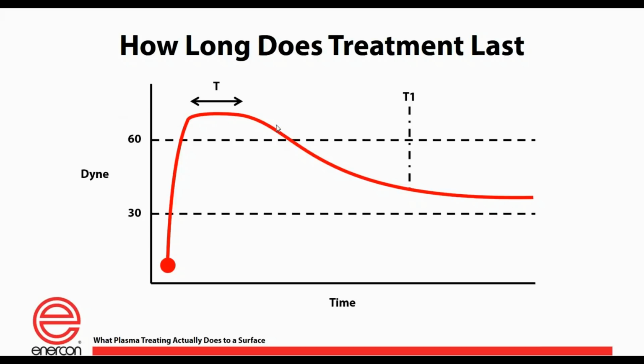Now, generally, you never get back to the surface energy level at which you started. In this case, again, about 10 dyne. We're going to steady state here at maybe 35 dyne. And the reason is that you have changed that outermost molecular layer. You've added functional groups to that surface that are not going away. And so that is why you have, in effect, increased the surface energy. So how long does it last?